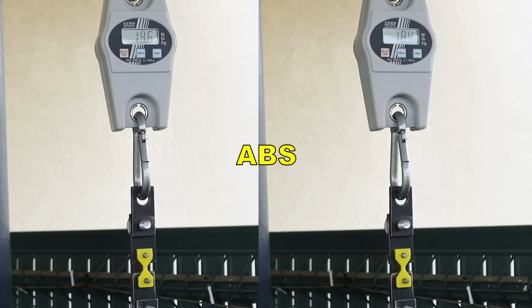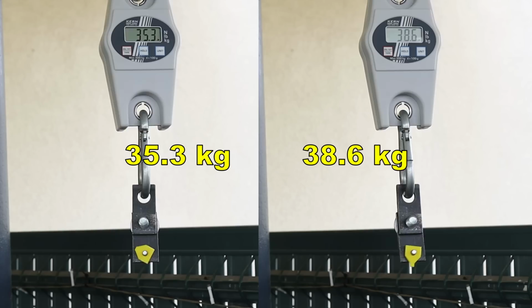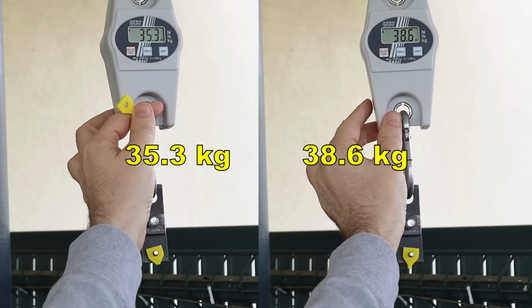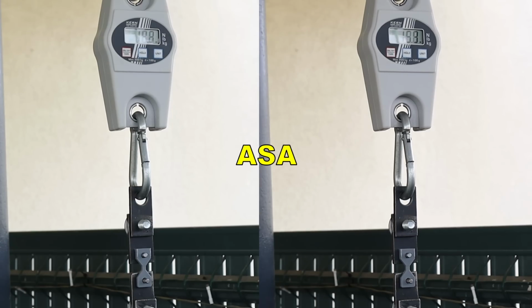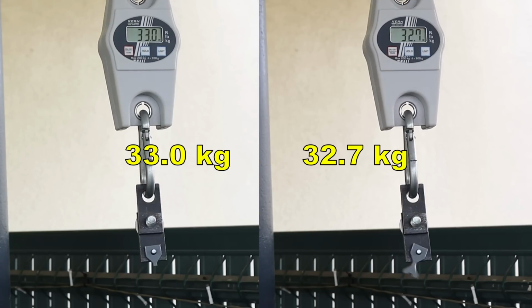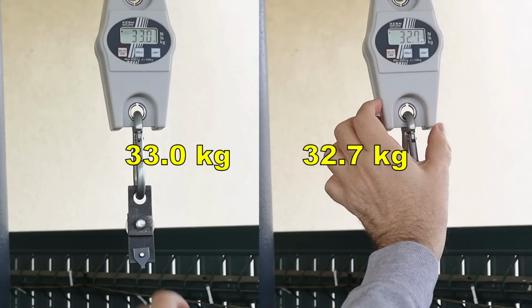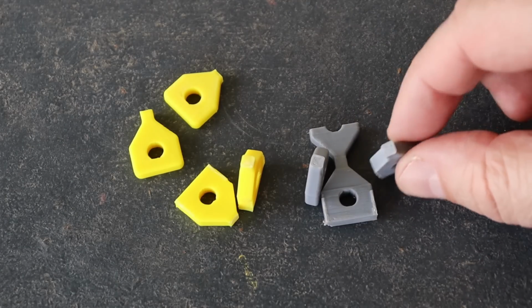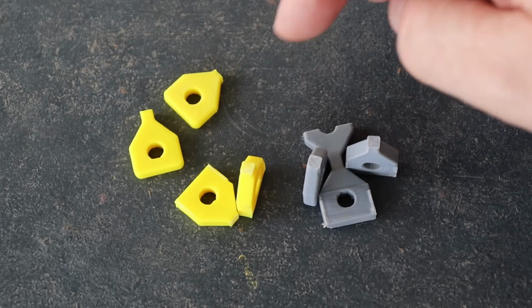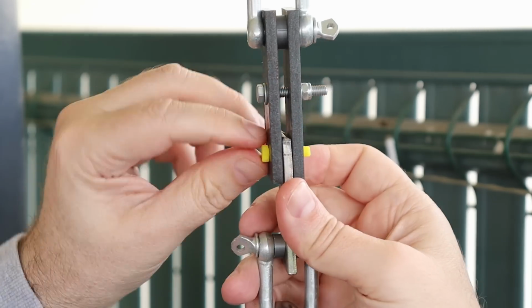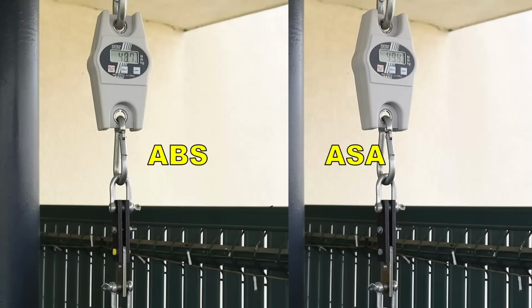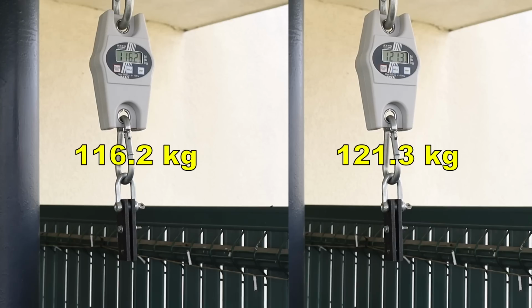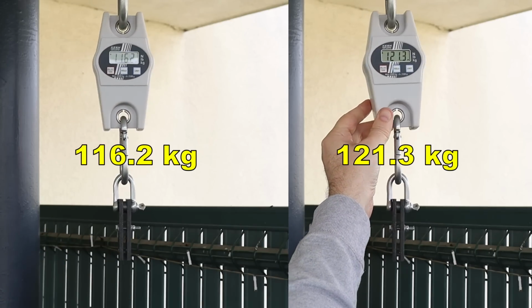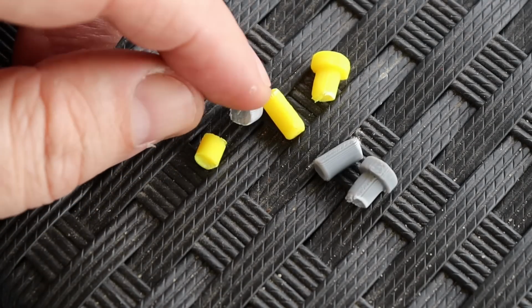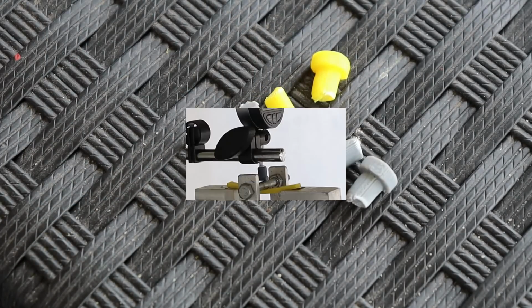These test objects are printed in vertical position. And this is very good layer adhesion, even for the ABS. And now ASA. This is again very good layer adhesion. And only one broke a little bit differently. And this is a two-sided shear stress test. Here you can see side by side ABS and ASA. And the break load was very similar. And they sheared correctly in 3 pieces on 2 cross-section areas.